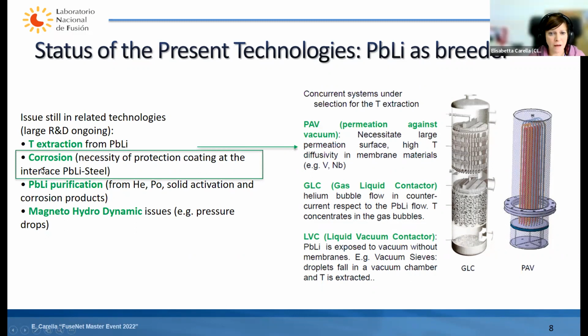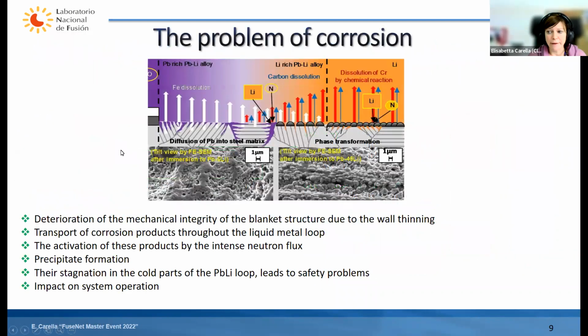For example, having a look at one important problem with materials, that is corrosion, we can see that the corrosion related to lead lithium brings some important problems. Why? Because we have the deterioration of the mechanical integrity of the blanket structure due to wall thinning, and the transport of corrosion products that can be carried out from the liquid metal loop and can also be activated by the neutrons present inside the breeder. We have the formation of some precipitates. Their stagnation in the cold part of the lead lithium leads to safety problems. So there is an important impact on the operation of the system.